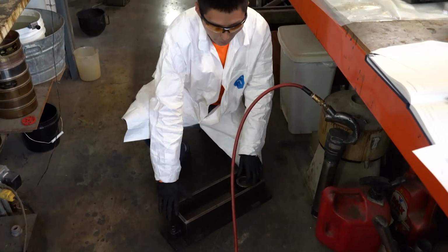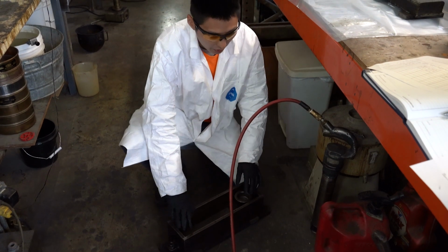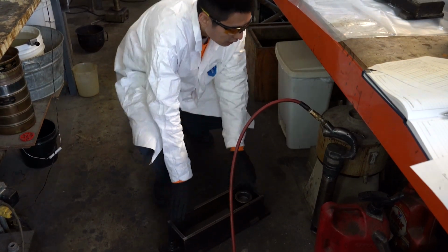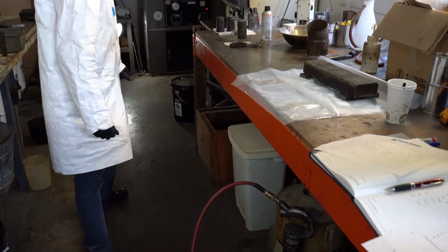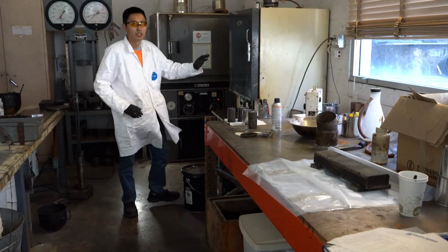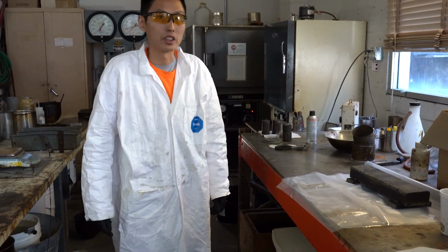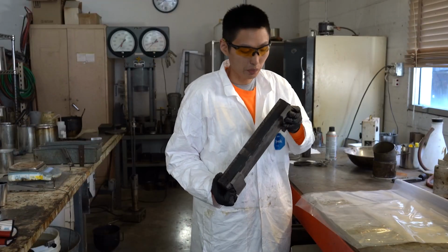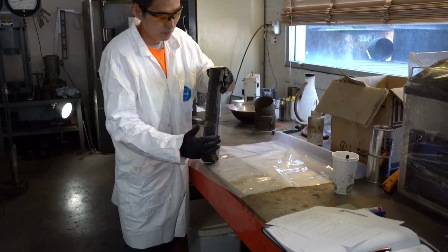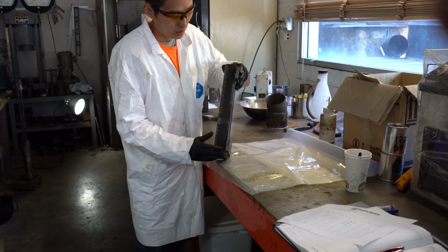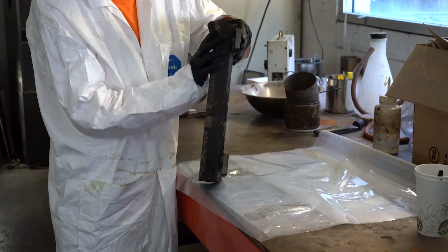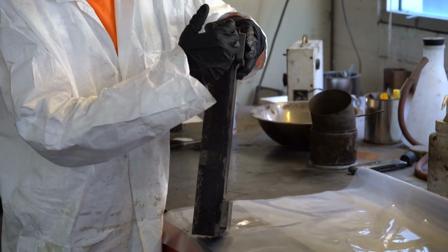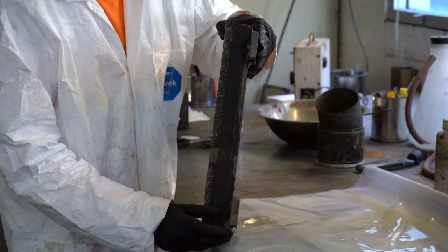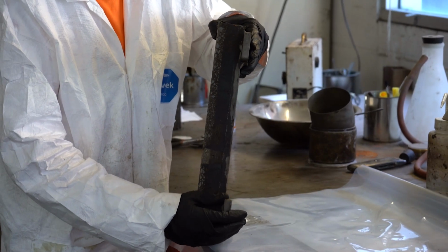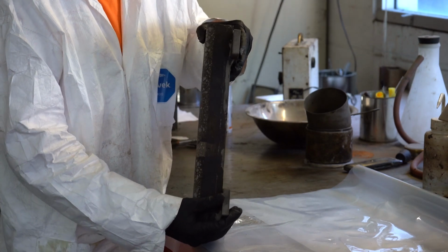And after the compaction is done, in the same way we move everything, which is about 40 pounds, into the oven for 4 hours curing, the same way we did for other epoxy asphalt samples. The final product will be like this. As you can see, the steel plate has been bonded very well with the epoxy asphalt concrete. The interface layer is the B1F bond coat we are using, and the overlay material is Type 9 epoxy asphalt mix. Type 9 epoxy asphalt binder.